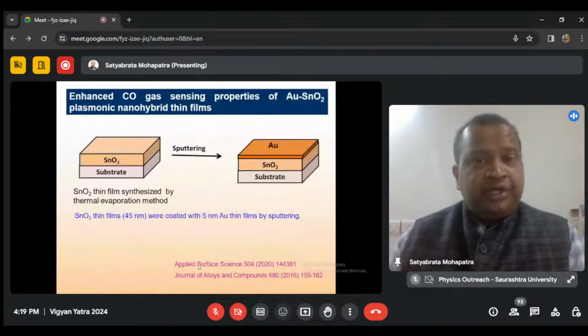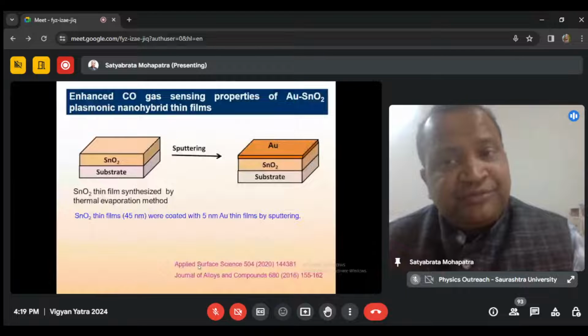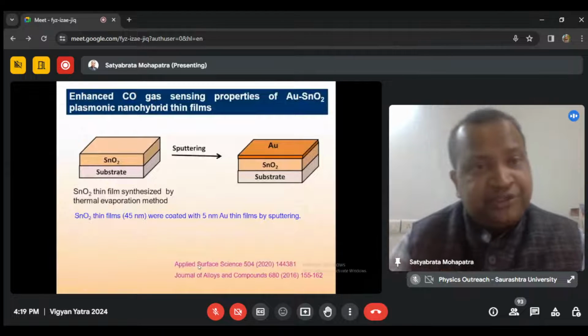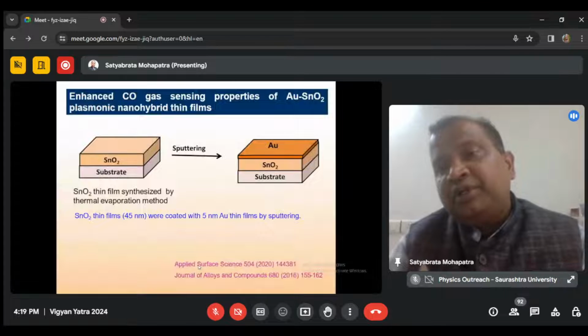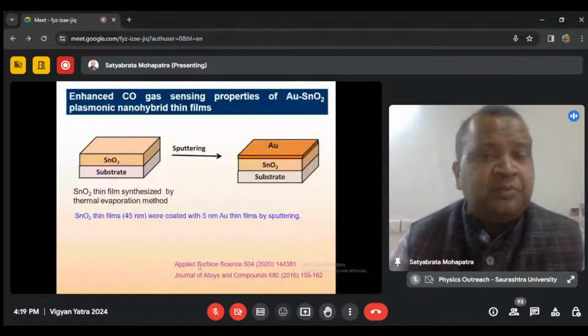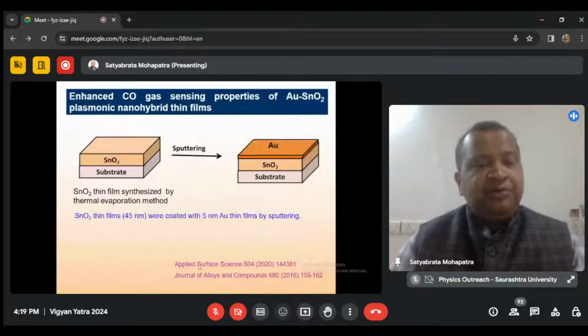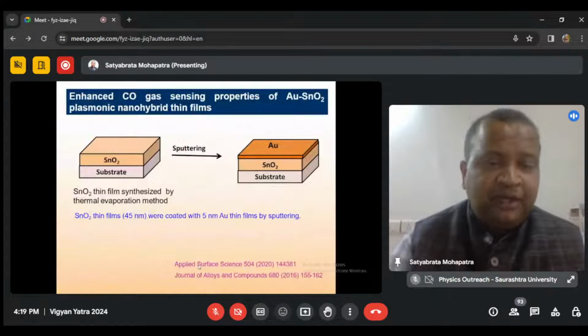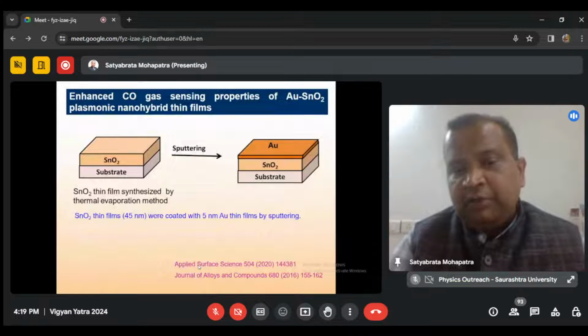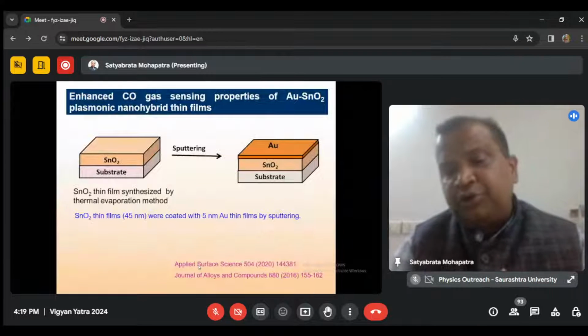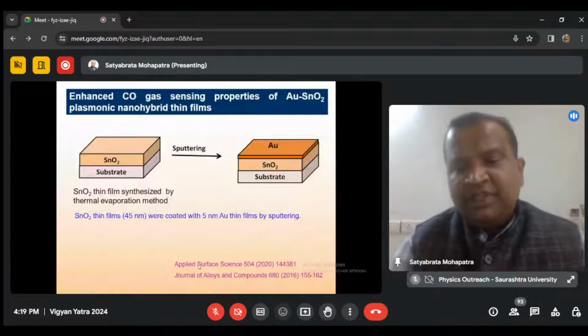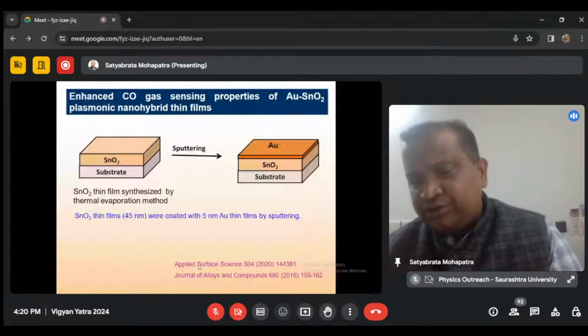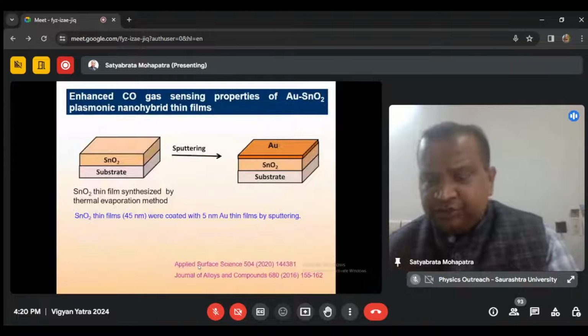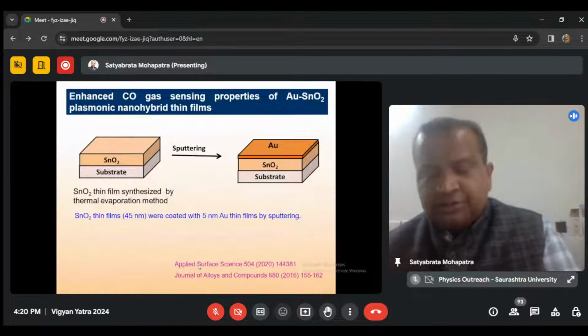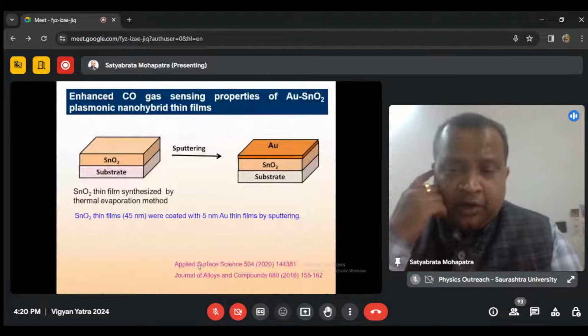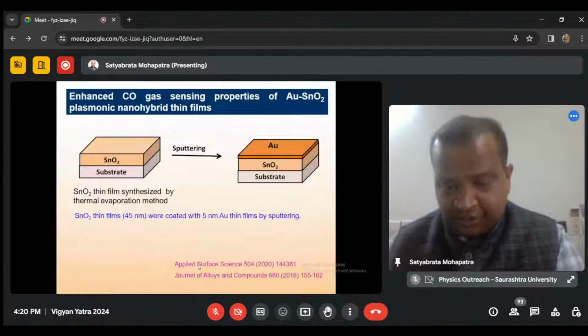In another study, we wanted to explore what happens if we make hybrids, gold-tin oxide plasmonic nanohybrids, which need thin film coating. For that, we coated 45 nanometer tin oxide films by thermal evaporation, and then we sputter coated a 5 nanometer gold film onto them. These studies came in Applied Surface Science in 2020 and in JALCOM in 2016. These studies are from one of my PhD students, Neha Bharadwaj.